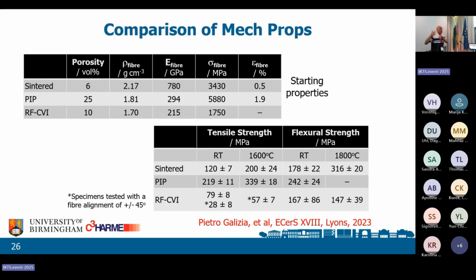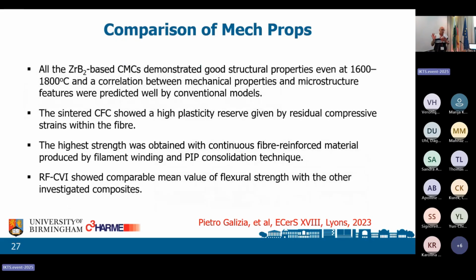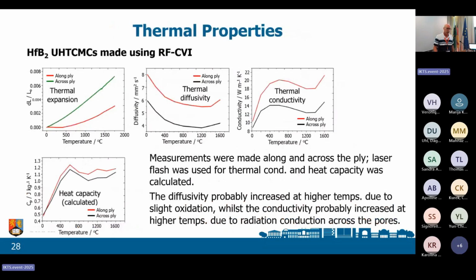Most people, when you say to them, for applications, what strength do you need? They say, oh, about 100 megapascals. And we're nicely over that in flexural strength. So there are advantages and disadvantages. These things give us good properties. We have a good performance generally that will get good strengths and good fiber pull out. I noticed the time, so I'm going to speed up just a little bit. We've looked at the thermal properties. We've mapped out the thermal expansion, thermal diffusivity, thermal conductivity, and heat capacity. So these are now able to be given to design engineers who can work on parts.